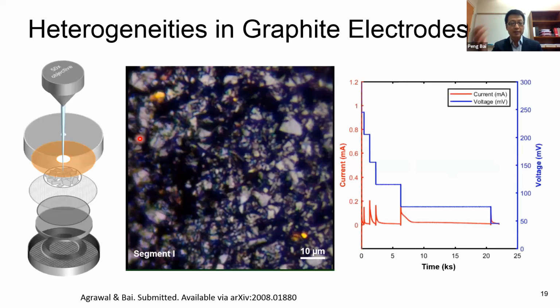So here, this is what my student Shobhan did. And we spent quite a long time to figure out the best configuration to characterize this graphite electrode. So in the middle, you can see here is a black electrode. It's black because it's graphite. It's the same material used in our pencil. But you can also see this gold stuff. It's not because we have some dust or gold coating. It's because when lithium goes into the graphite, it can change color. So let me now play the video.